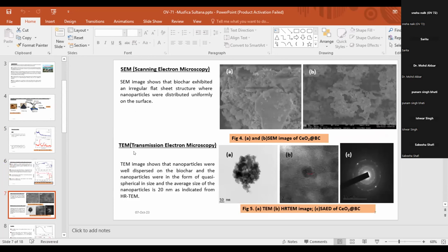After that, SEM and TEM techniques are applied. From the SEM images, it is shown that biochar exhibited an irregular flat sheet surface where nanoparticles were distributed uniformly on the surface. From the TEM image, it shows that the biochar and nanoparticles are well dispersed, quasi-spherical in shape, and the average size of the nanoparticles is 20 nanometer as indicated from HR-TEM.